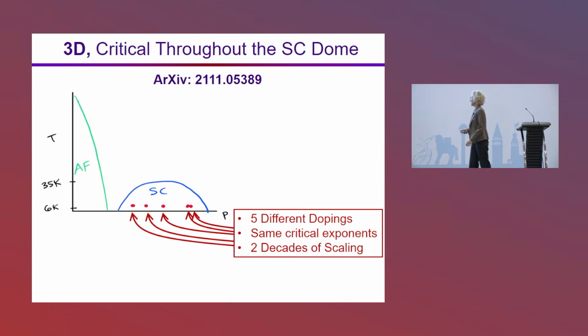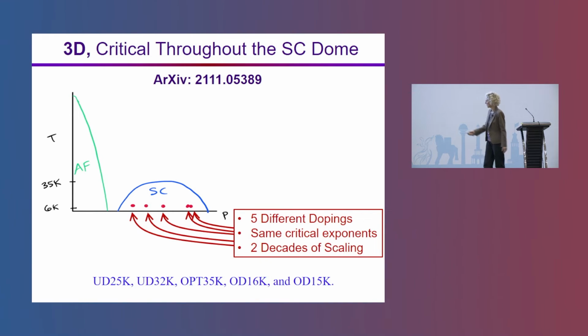However, what was curious is that we could not detect a change in the correlation length. I was expecting that as a function of doping, we would see the correlation length blow up at a particular doping, and that would be the critical doping. But in fact, we just see 2 decades of scaling throughout. It's power law scaling throughout their entire field of view. So the correlation length exceeds their field of view throughout this entire doping range. These are the different dopings: 2 different underdoped, optimally doped, 2 different overdoped samples.